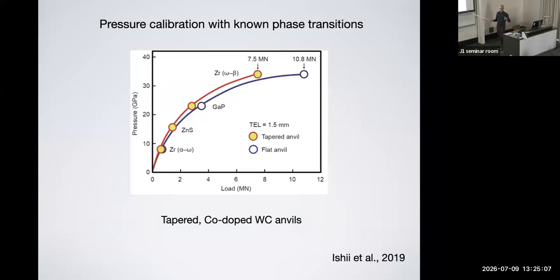Oh, yeah, pressure calibration, there's all sorts of things that go into the background here. The pressure calibration is done by looking at known phase transitions, right? So you have all these materials here that have phase transitions in that pressure range, of course, up to, in this case, 40 gigapascals. So there's lots of background work before you can actually do these kinds of experiments.